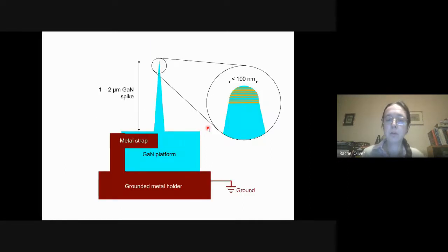So what we wanted to do was do that to gallium nitride. Now, this was several years ago now, and this is something that's done fairly commonly on semiconductors at this stage. But at the point when we did it, no one was doing it on semiconductors. So the first thing we had to do was work out how to make a really sharp needle with our indium gallium nitride quantum wells at the top, because that sharp needle is what lets you get the high fields, which is what facilitates the whole atom probe technique.